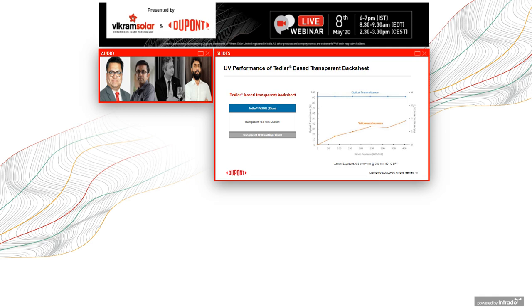Once we have the Tedlar film, now obviously the backsheet is, as I pointed out, made out of this Tedlar film on the outer side, and then a transparent PET core and an inner layer. This is also a fluorinated coated layer. On the right, we are showing how this transparency, the optical properties, holds up after 400 kilowatt hours of UV exposure from a xenon source, which actually simulates the sunlight the best way.